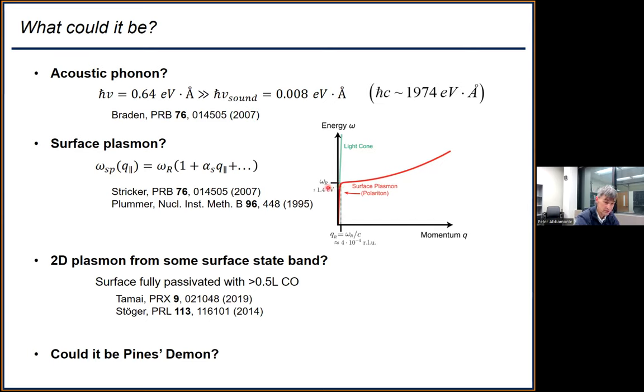So then we thought, could it be maybe a collective mode from a surface state? A lot of materials that cleave, there's a surface state there, and then you can get a gapless collective mode because there's a 2-deg on the surface, and all plasmons in two dimensions are gapless. Things like that have been seen in beryllium, copper, other things.